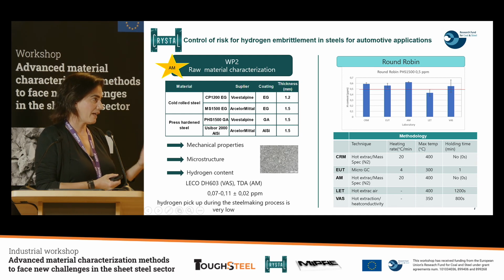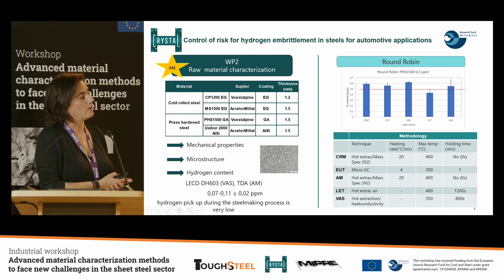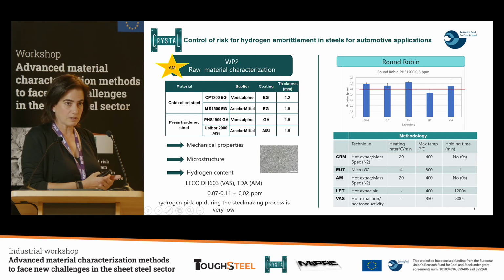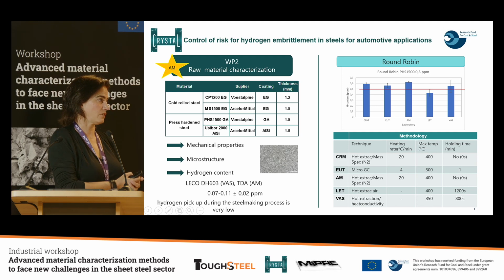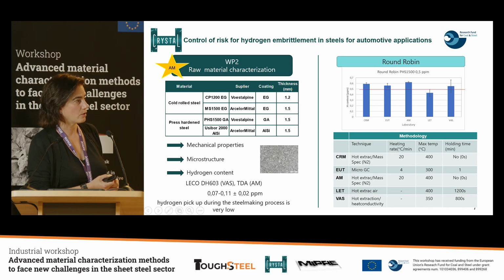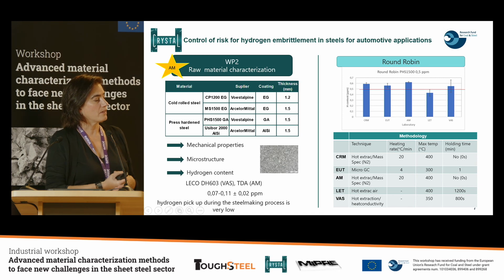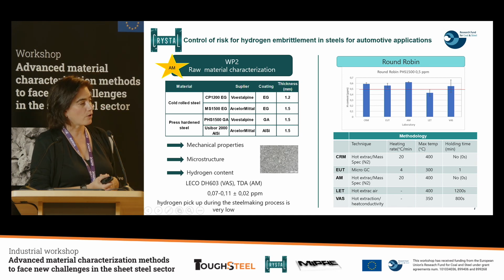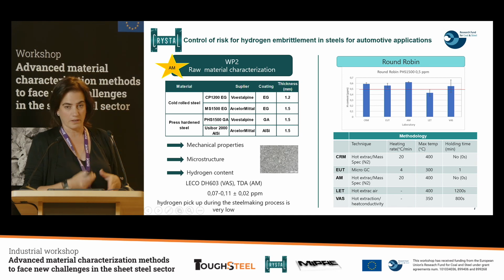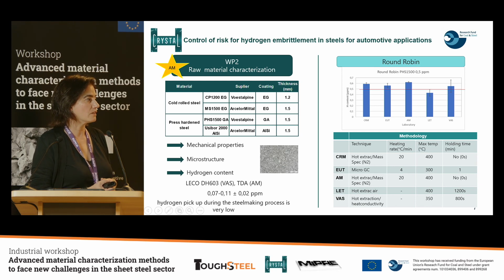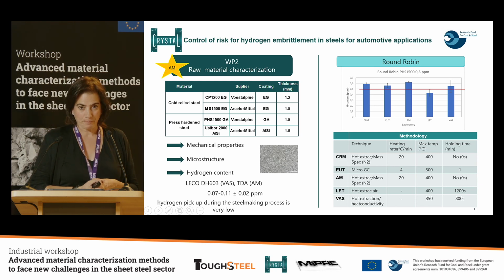In terms of mechanical properties, we also evaluate or analyze the microstructure, and we determine the hydrogen content in this steel process. We used 2 different techniques, LECO DH603 from voestalpine and a TDA equipment from ArcelorMittal. As you can see, the hydrogen content measured was from 0.07 to 0.11. So the hydrogen pickup during the steelmaking process is very low.